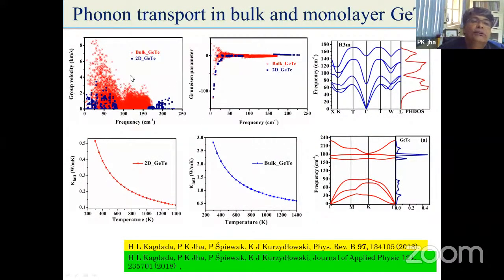Now here you have the group velocity, you can see for the bulk GeTe, right? You can see that for the bulk GeTe, the group velocity is very large, up to 8. But for the two-dimensional GeTe, the group velocity is lower. And as we have discussed, if the group velocity is lower, the lattice thermal conductivity will be lower, right? Similarly, for the Grüneisen parameter, you can see, but this is interesting to observe, right? And therefore, the lattice thermal conductivity for two-dimensional GeTe is maximum 0.5 at 300 Kelvin, while in the bulk GeTe, it is around 3 at room temperature. So the point is that for the monolayer, you can have the lower lattice thermal conductivity. That means it is nothing but nanostructuring the material, right?